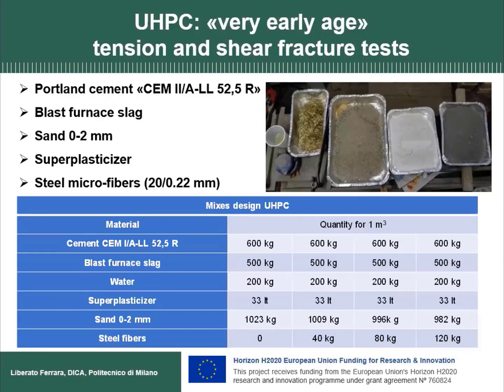We investigated a reference mix with no fibers, the matrix, and three different fiber dosages equal to 40, 80, and 120 kilos. These are still microfibers, 20 millimeters long with a diameter of 0.22 millimeters, so the aspect ratio is about 90. These dosages correspond to 0.5%, 1%, and 1.5% by volume.